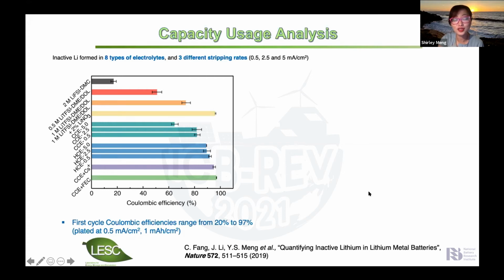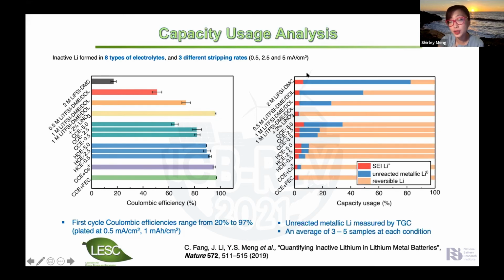Thank you very much. So let me continue to talk about the lithium metal anode. When you have different electrolytes, you can see the good ones and the bad ones have very different Coulombic efficiency. According to our measurement, indeed, most of this Coulombic inefficiency comes from the lithium that's trapped, the blue part, in the SEI due to the electronic contact loss.